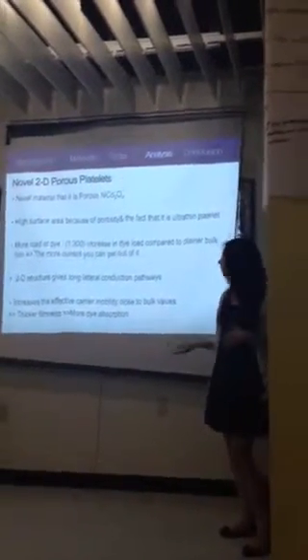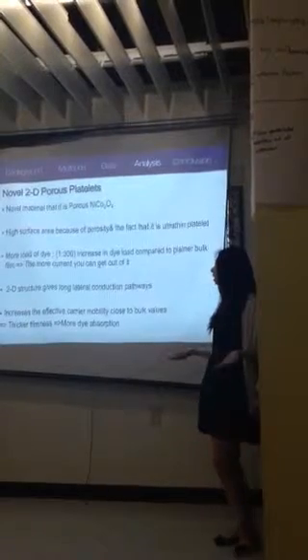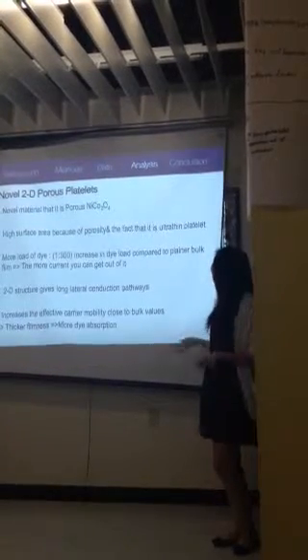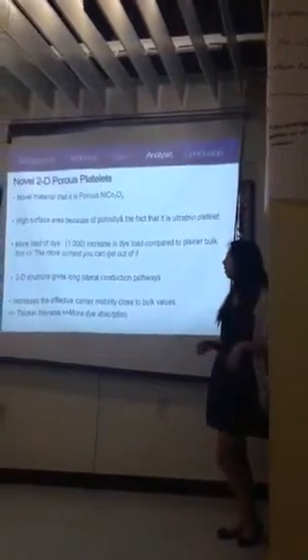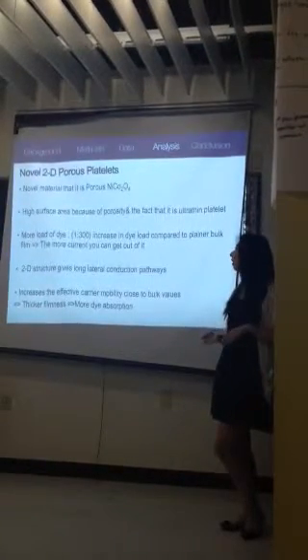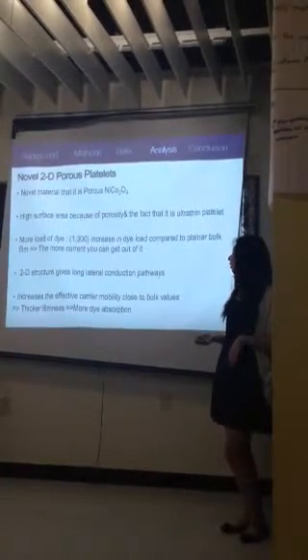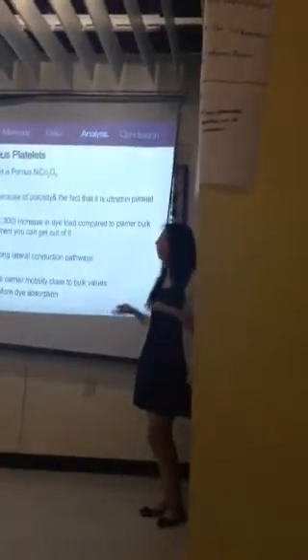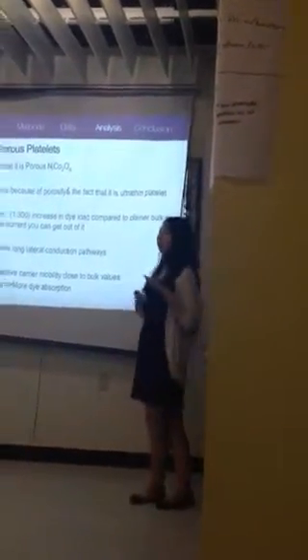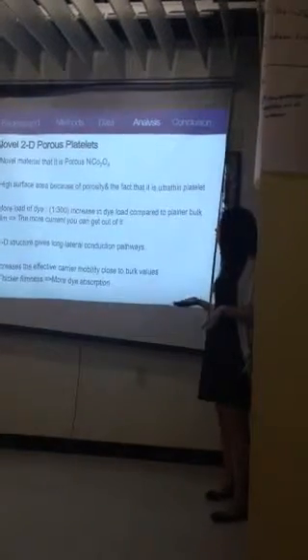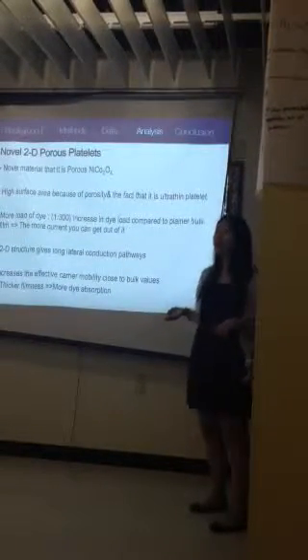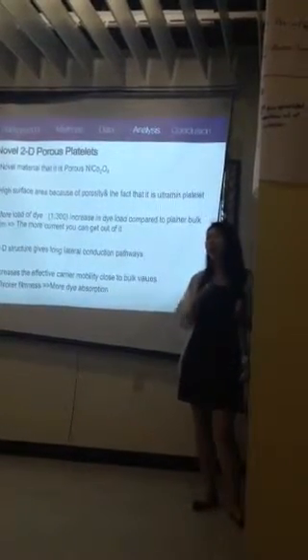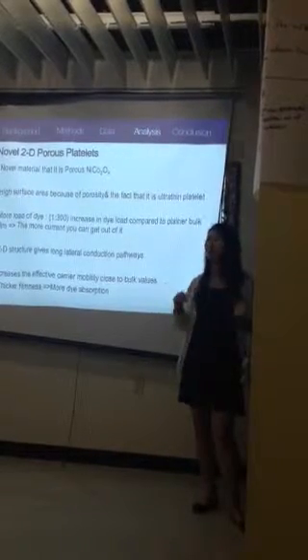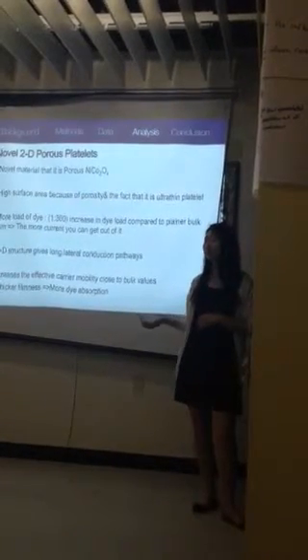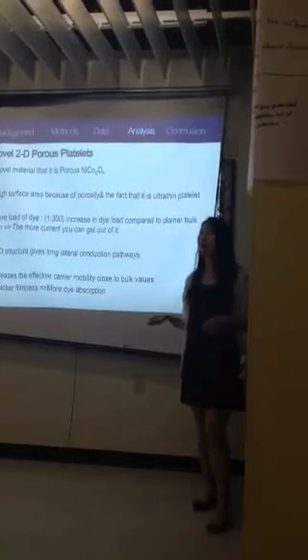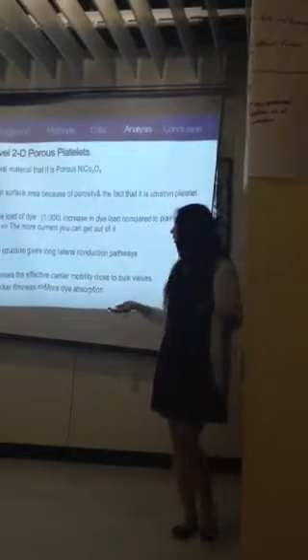With a high surface area, it can load more dye, about 300 times more than the plain bulk film. And the more dye you load on it, the more current you can get out of it, so basically it means better efficiency. Also, the 2D platelet structure gives very long conduction pathways, which means a carrier travels a longer pathway before it jumps to the next platelet, so you have a lower possibility of recombination, which also increases the efficiency.